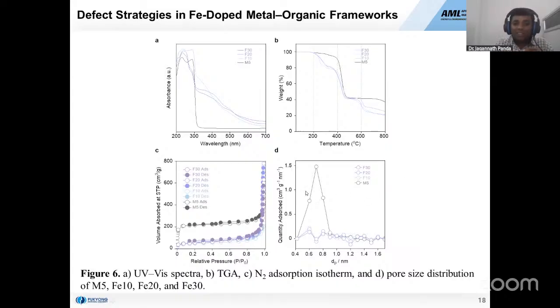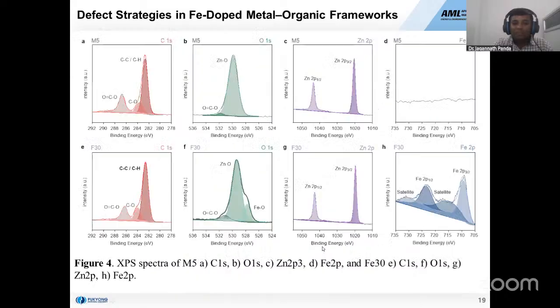Then this is the pore size distribution. In the case of M5, there is a big pore, but a similar pore is also available in the case of the defect MOFs. Then we also performed the XPS spectra to identify the oxidation state of metals like iron, whether present or not. We got that there is no disturbance in the framework.